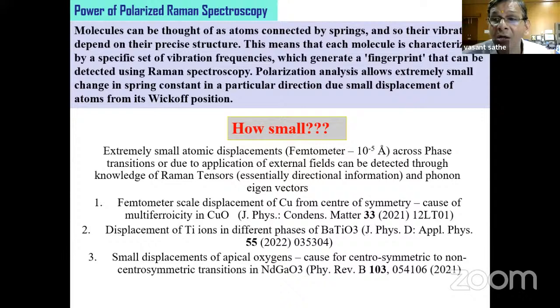But such a small displacement can also be found out if you do very careful experiments, which we showed, in a single crystal or potential film, because polarization means direction dependence. In polycrystalline, there is no direction which is well defined. So we need a single crystal or something. And we came up with these three papers. That is, we solved the mystery of why CuO becomes ferroelectric below 230K by doing this particular part.